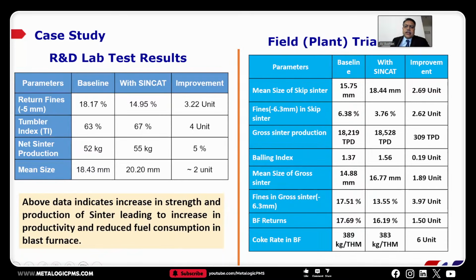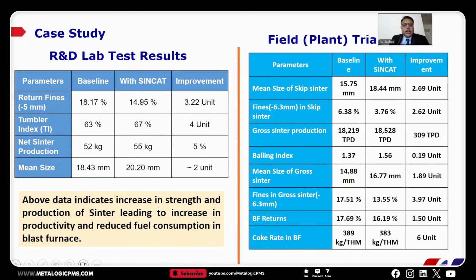So these are the case studies actually. We have taken trials of the product at our own R&D, and these are some of the results that we have got. We have also done a commercial scale plant trial in one of the plants in India, and we have got very good results, which is displayed on the right side of the screen, the field trial results. So let me go through the R&D lab test results. You can see the reduction in the sinter fines was very significant, 3.22 unit reduction. Similarly, there was an improvement in the tumbler index, and of course, the improvement in mean size. The increase in the mean size obviously has a huge impact on the performance of the sinter and the blast